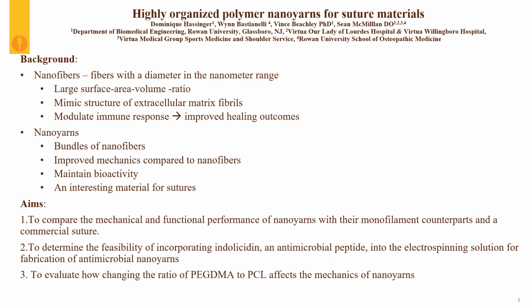it leads to improved healing outcomes. We're particularly interested in nanoyarns, which are bundles of nanofibers. As a bundle, they have better mechanics than the fibers on their own, yet they still maintain this bioactivity because they're composed of these nanofibers with a high surface area to volume ratio. So we think these are a really interesting material for sutures, given that they can meet some of the current limitations due to the surface functionalization capability.